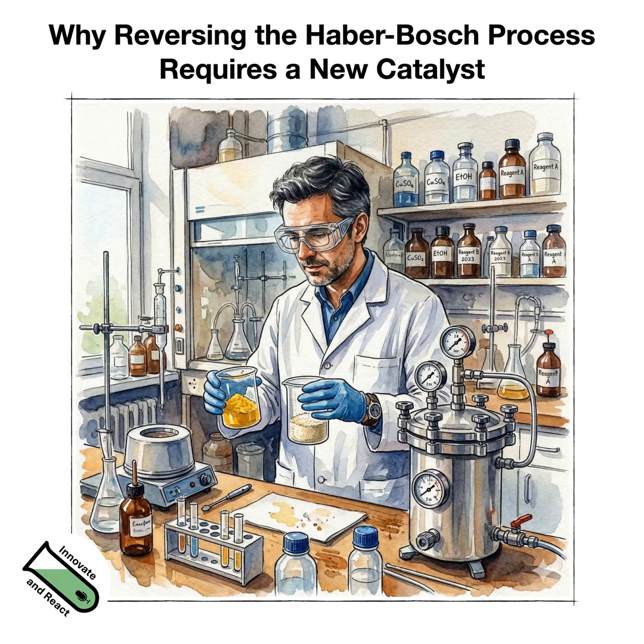So those catalysts really look like a metallic sponge more than a typical supported system, where you have an extended porous but inert material with very small nanoparticles of noble metals. That allows us to increase the number of surface sites per reactor volume. Typically in large scale production, you have a large investment to create the reactor. It has a certain volume, and you need to fill as many surface atoms in there as possible. And it's not so important whether you also fill in bulk atoms, if you don't need to pay a lot of money for them.